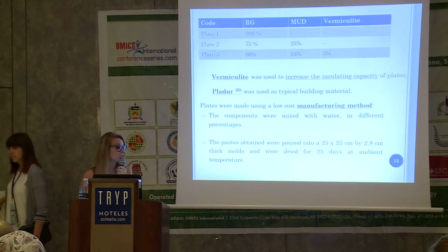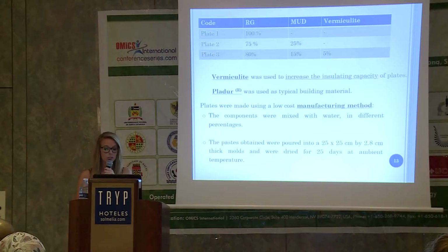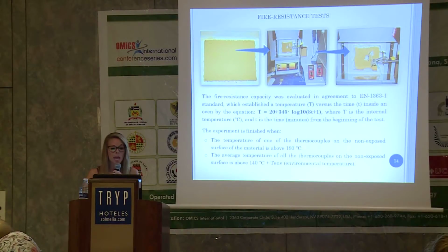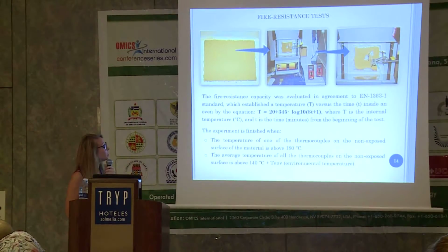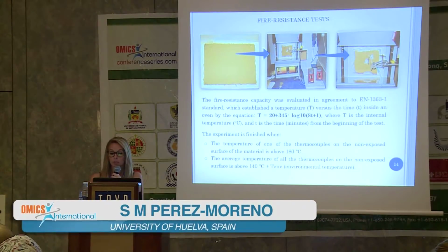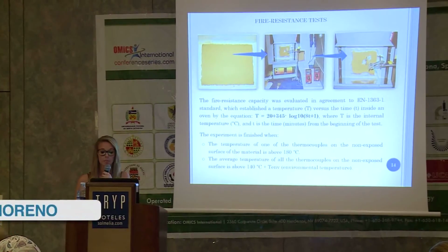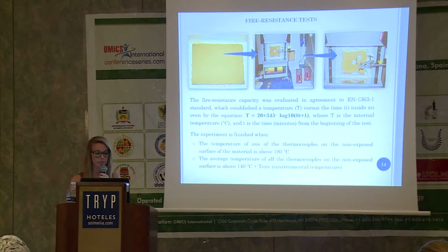Plates were made using a low-cost manufacturing method. The components were mixed with water in different percentages, and the pastes obtained were put into a mold and dried for 25 days at ambient temperature. The fire-resistant capacity was evaluated in agreement with the EN 1363-1 standard, which establishes a temperature versus time curve inside an oven by this equation.